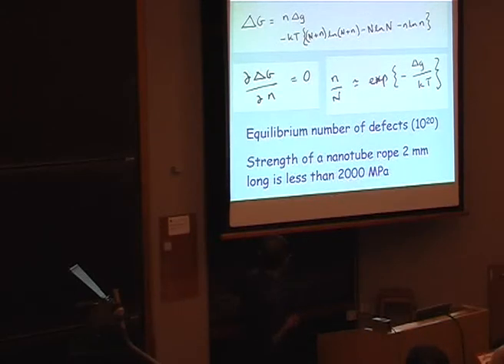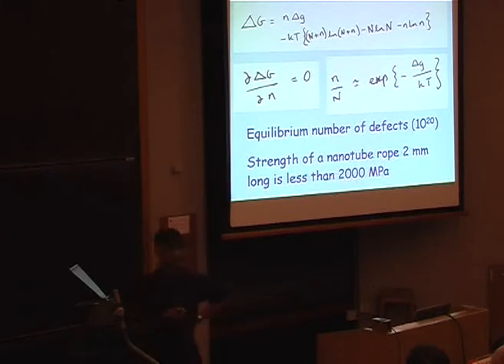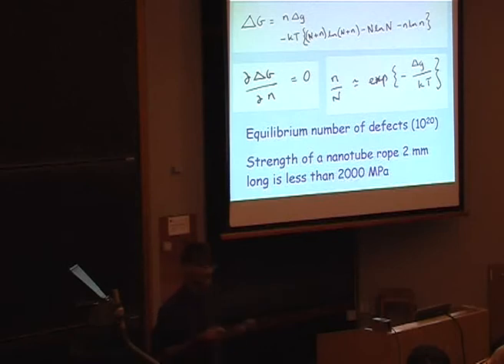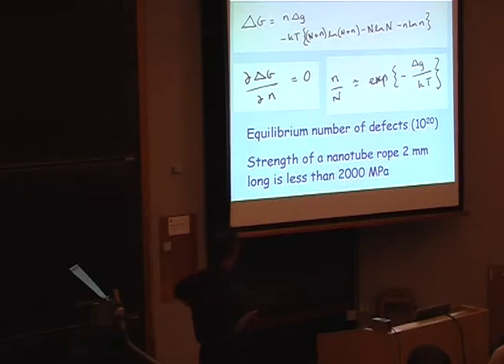I calculated the number of defects I should find in the rope that is being considered for making a space elevator, okay, out of carbon nanotubes. There will be at least 10 to the 20 very severe defects inside that nanotube under equilibrium conditions. So there is absolutely no nanotube which exceeds the strength of steel beyond the size of 2 millimeters.